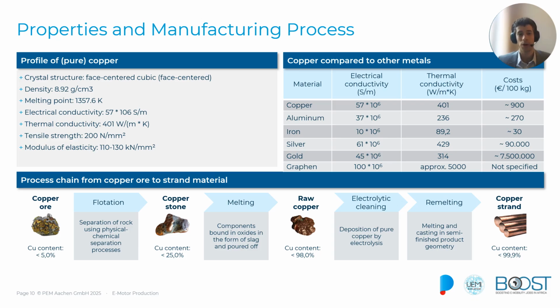But we also see some interest in aluminium as a conductor material today, due to its even lower cost than copper. And graphene is a future material out of carbon and not usable today as a conductor. We also have good thermal conductivity with copper and a high melting point, which allows us to supply it with high current strength.